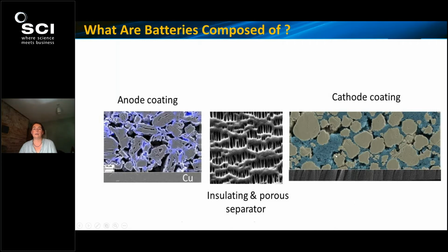The electron image on the right shows a cross-section through a cathode coating. This is based on a transition metal oxide. And as you can see here, there is a not very uniform distribution of conductive additives. The electrodes are all separated by an insulating and porous separator, which is typically a tri-layer laminate based on polyethylene and polypropylene.